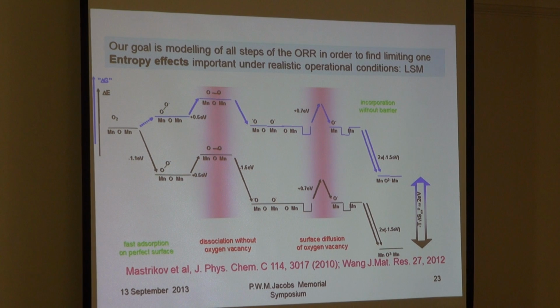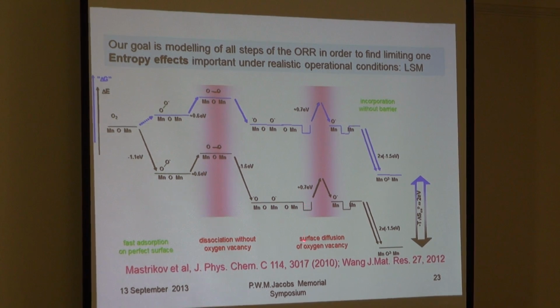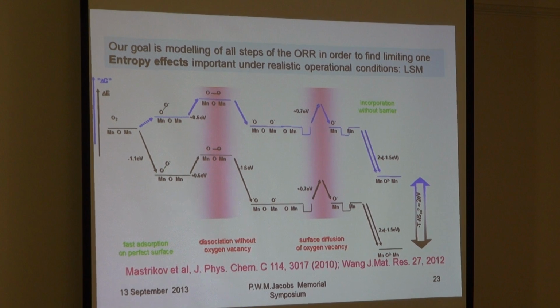And next, again, the question is how these adsorbed oxygen atoms meet surface oxygen vacancies, because this is just the first process which triggers oxygen penetration into the first plane and next migration through the cathode material to the anode. So we need a reaction between surface vacancy and adsorbed oxygen. And again, experimentally you can't discriminate which is more mobile, because it's essentially a diffusion-controlled reaction.